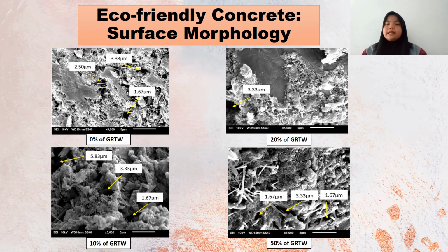Eco-friendly concrete surface morphology. SEM image of the concrete with different weight fractions of GRTW obtained with a magnification of 5,000. The concrete containing 20% GRTW has fewer pores compared to 0%. The microstructure of 0% GRTW concrete shows that pores of larger width are present in the concrete while the concrete is not densely packed. Those results prove that the use of recycled ceramic aggregate can modify distinctly the structure of the concrete.